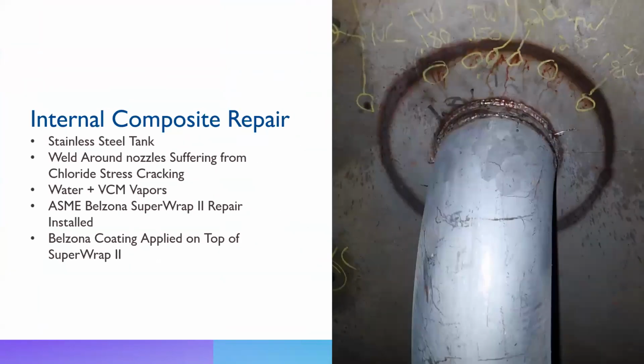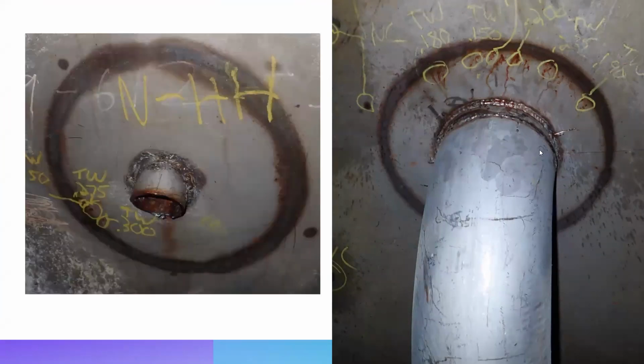So again, kind of same scenario here. This is the tank. It had some chloride cracking right at the nozzles, so right around the welds, which is going to be your most susceptible area. As you can see, they did a dye penetrant and found the cracks. This was in the vapor space, and it had vinyl chloride monomer, which is most likely your source of the chlorides. And we, again, went for the same system.